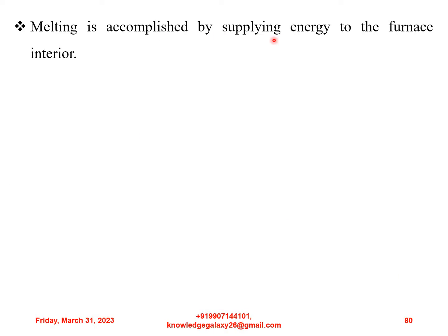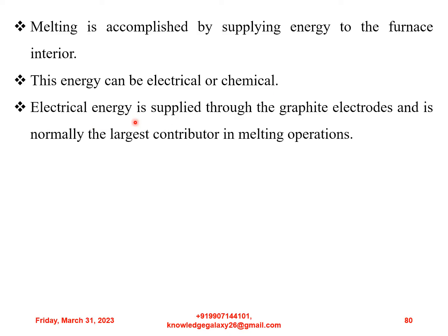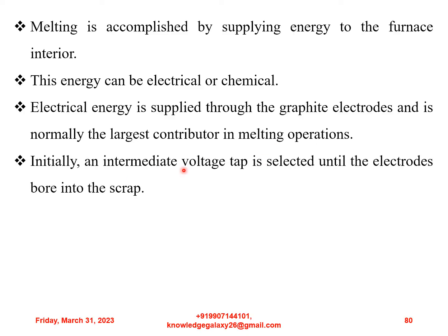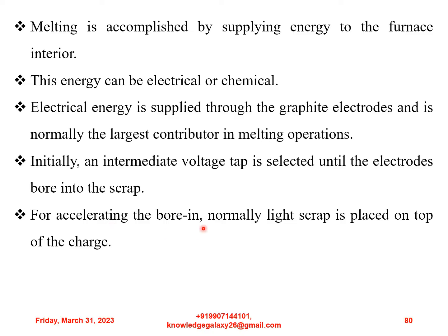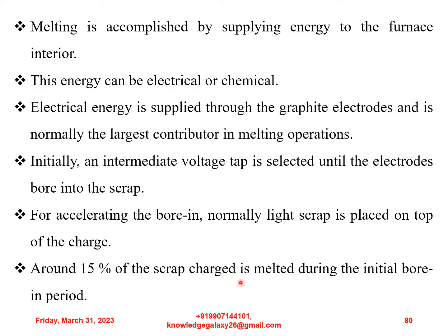Melting is accomplished by supplying energy to the furnace interior. This energy can be electrical or chemical. Electrical energy is supplied through the graphite electrodes and is normally the largest contributor in melting operations. Initially, an intermediate voltage tap is selected until the electrodes bore into the scrap. For accelerating the bore-in, normally light scrap is placed on top of the charge. Around 15% of the scrap charge is melted during the initial boring period.